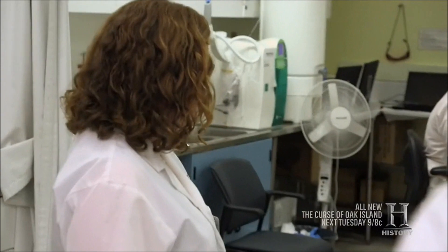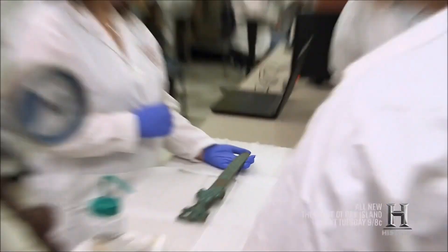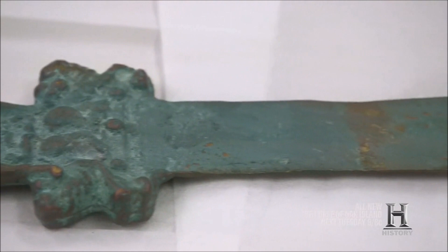So when people are dealing with a copper alloy artifact, usually the first question they're interested in is: is this a bronze or is this a brass? Based on whether it's a bronze or a brass, it's really helpful in terms of dating the object. So what we did is, on the back down here at the polished tip, we removed some shavings — filings of the base metal — and that allows us to basically look at the composition of the alloy. The base metal in this case is a copper-zinc alloy, so that tells us right away that this is a brass.